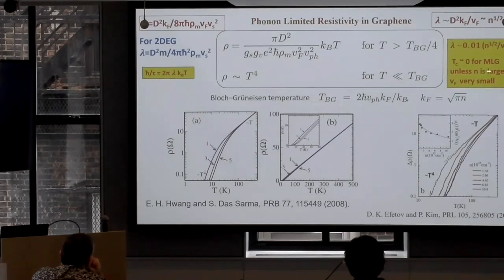There's a very good paper by Chubukov, Rahul Nandkishore and Levitov, where the idea was that if you can push the density all the way to the Van Hove singularity of real graphene, which is almost 10 to the power 15 per square centimeter doping, then you'll get superconductivity. And there is an interesting story about this paper. In fact, that's what Efetov's thesis was supposed to be. He was supposed to dope graphene to the actual Van Hove singularity and see superconductivity coming from electron-electron interaction. But what happened is they could not dope that high. They could only go to 10 to the power 14.